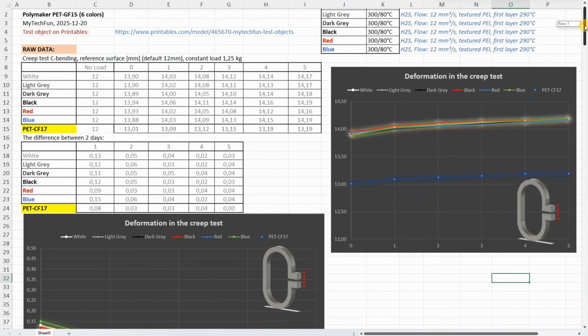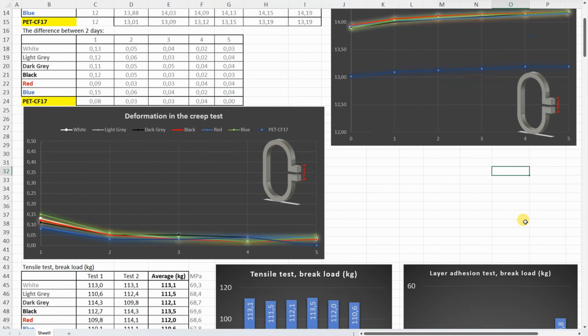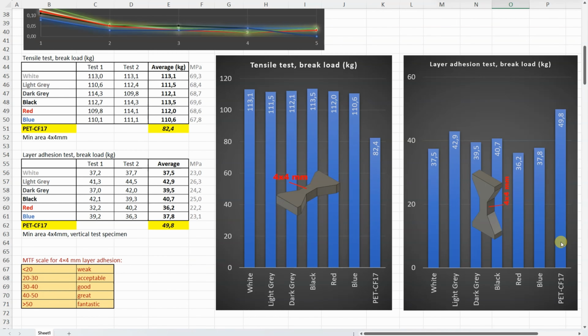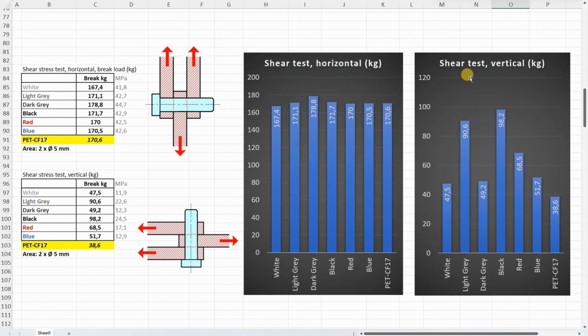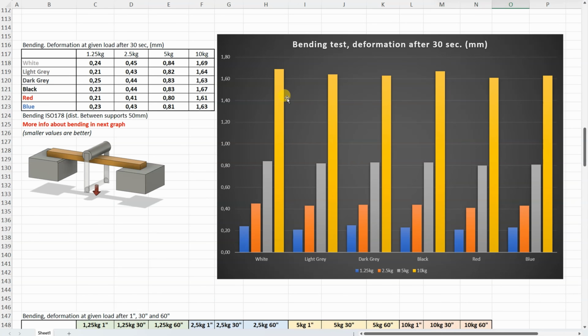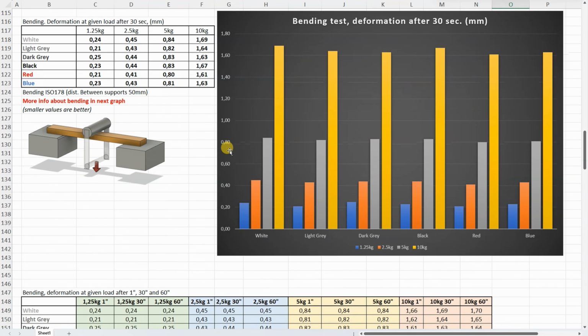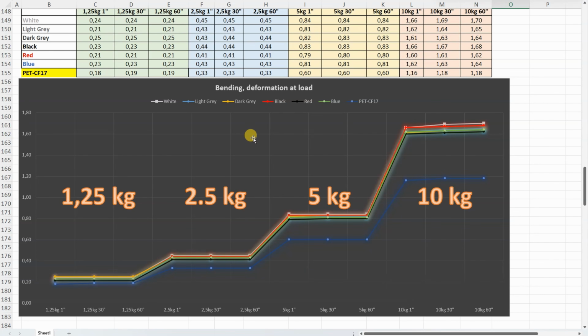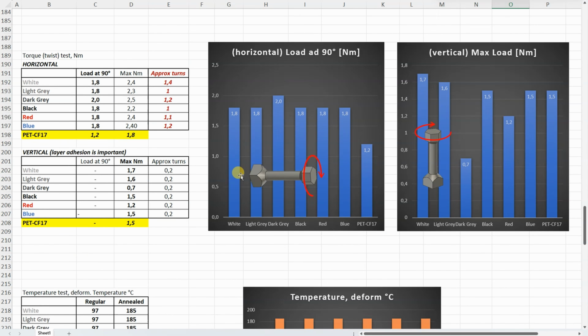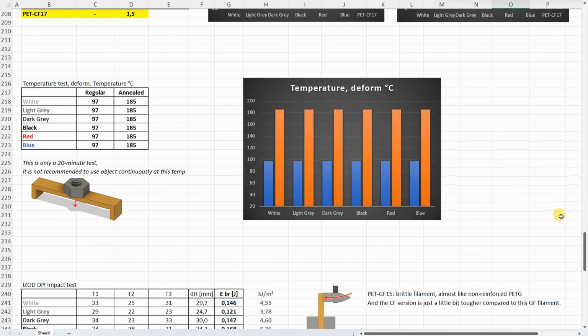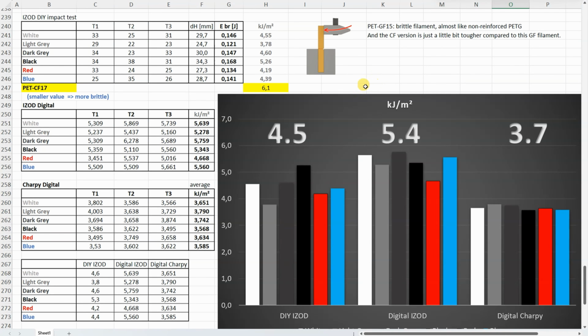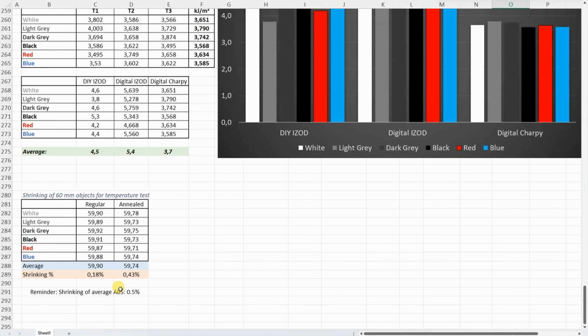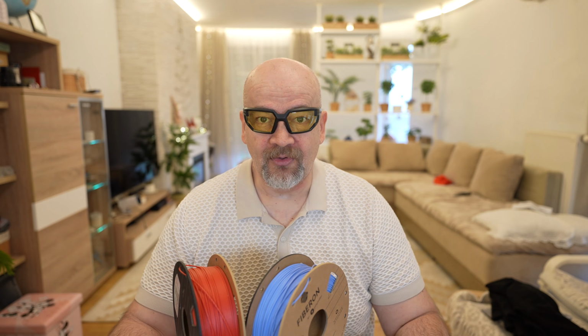All results one more time without any additional comment. This is the result for the creep test, tensile test and the layer adhesion, shear test horizontal and vertical, bending, deformation after 30 seconds, bending test, deformation after 1, 30 and 60 seconds under these loads, torsion test horizontal and vertical, temperature test, impact test, IZOD DIY, IZOD digital, Charpy digital, summary for all 3, and these are the average values, and the shrinking. Wow, this was so big work that I don't really want to repeat it.